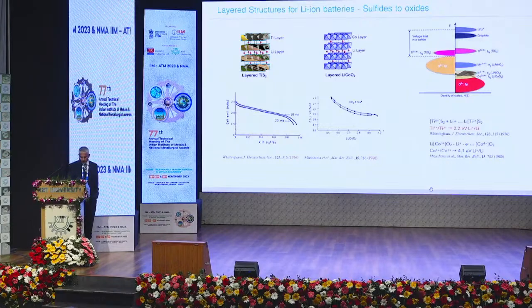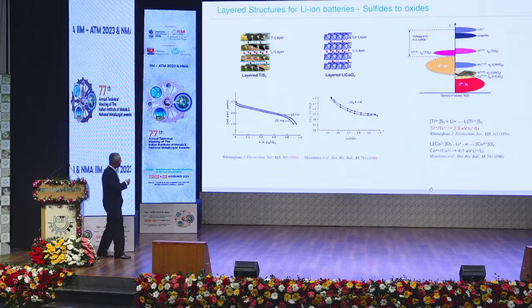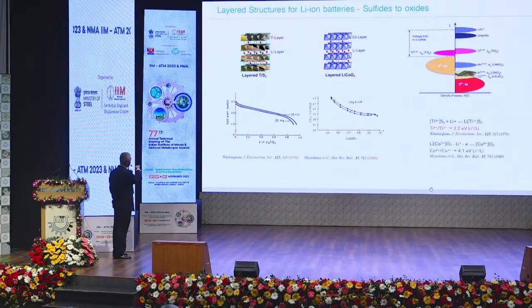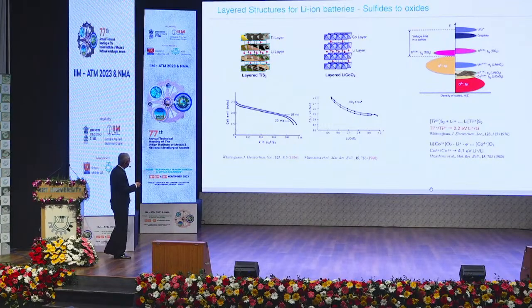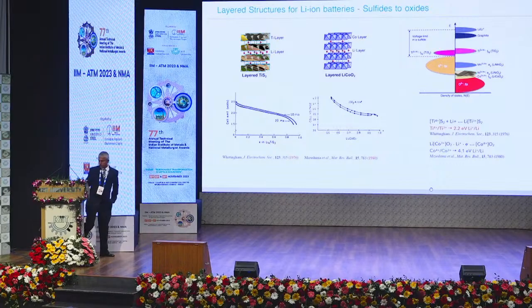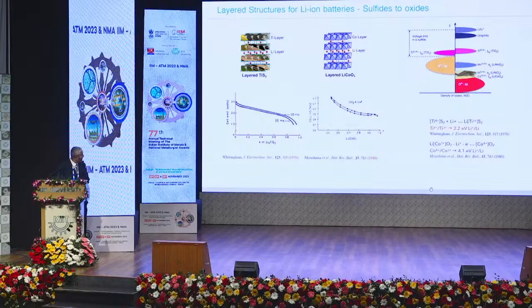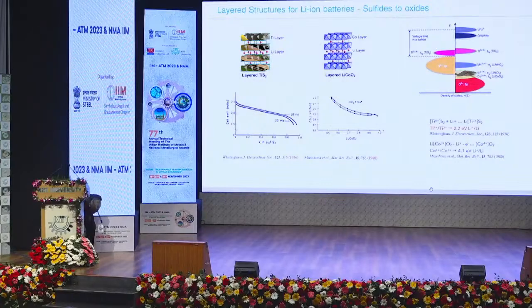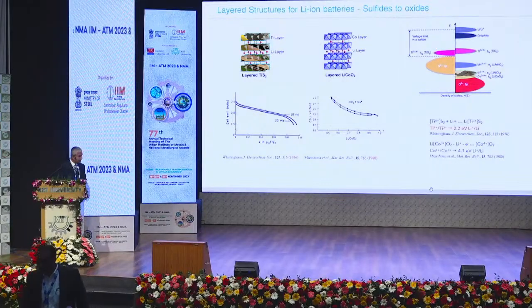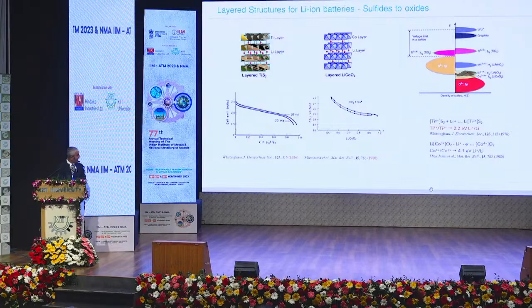So the professors could find another structure, which is the same as TiS2, and they could increase the voltage of the cell to 4 volts by just using cobalt oxide. So the cobalt 3+ in the oxide, by extracting lithium, gets oxidized to cobalt 4+. This particular development spurred a lot of other materials, like lithium nickel oxide or lithium manganese oxide, or the current-day NMCs that we use.